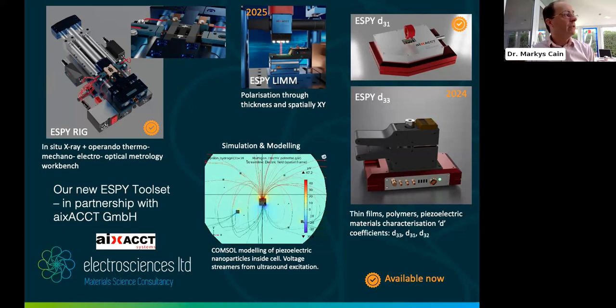If you get a swelling, you'd get an additional stress, probably hydrostatic stress on the piezo particles, which would impact your measured value of d33. I think that's going to be a mixture of decoupling the measurement of charge in your system, which means you might have to use a slightly different system to do that decoupling, because it's coupled so well to the sample that's in series with your sample in the piezo test machine. That's the problem with that tool.